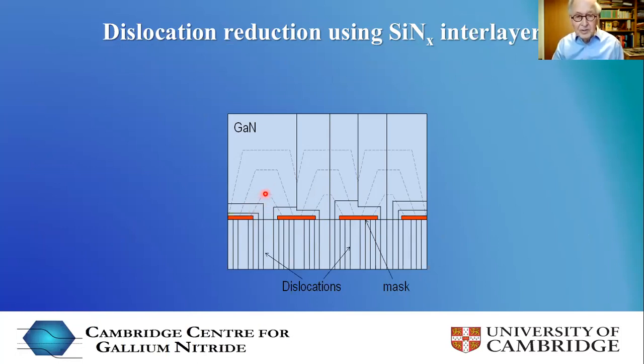But we can reduce it further, because when we start to grow on top of the masks, we alter the growth procedure, so we alter the growth mechanism. Underneath this silicon nitride layer is layer-by-layer growth of gallium nitride. Above the layer we have island growth - you get these faceted islands. And when the dislocations which come up through the hole hit the side face of the facets, they bend sideways.